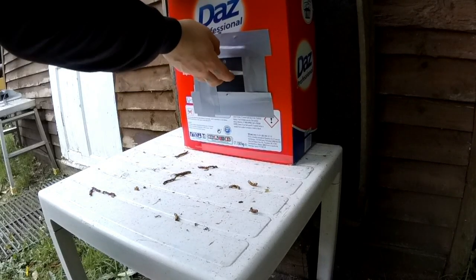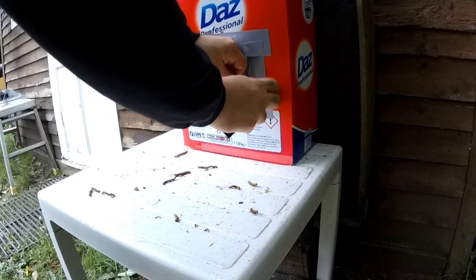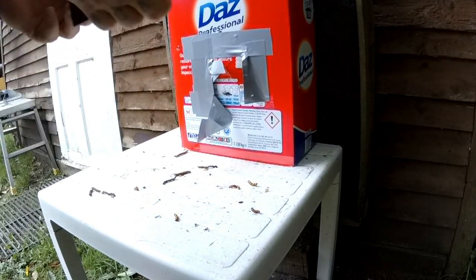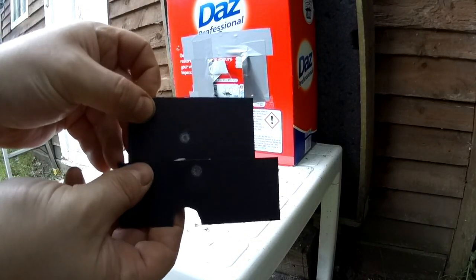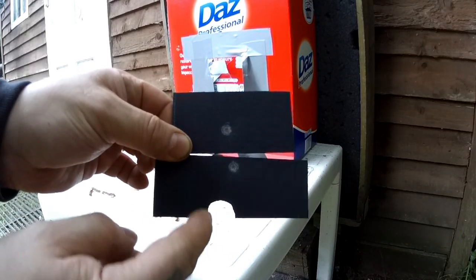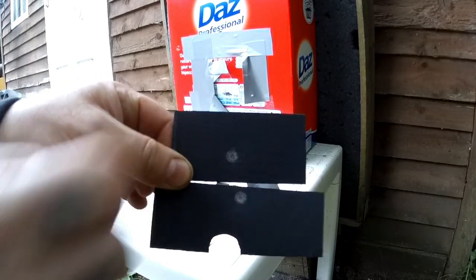That was two pieces that didn't actually crack there. So the 2mm Kydex did stop the pellets. The bottom cracked on the edge, but I suspect you could just reinforce the edge with a piece of metal if you wanted to. So 2mm Kydex will actually stop pellets.